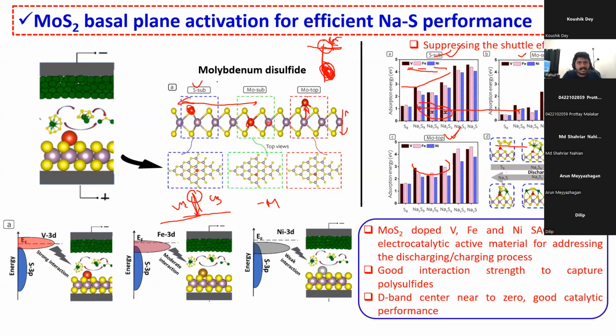Now, keeping all these things in consideration, we studied vanadium, iron, and nickel here. This line is the Fermi level, and this is the d-band center. The d-band center for vanadium is close to the Fermi level when compared to iron and nickel. Nickel is very far from the Fermi level. But for vanadium, the d-band center is close to the Fermi level. That's the reason why vanadium can easily fill the electrons. Because of easily filling the electrons, you can see that vanadium has the highest binding energy when compared to iron and nickel. Why? Because its d-band center is very close to the Fermi level. If the d-band center is very close to the Fermi level, the adsorption energy is very high.